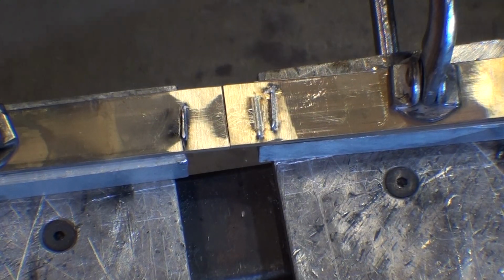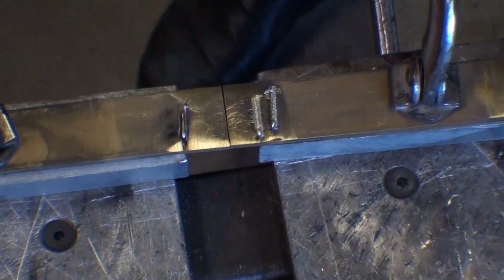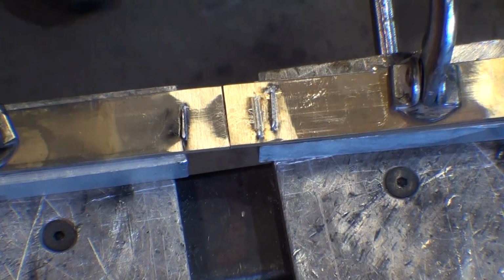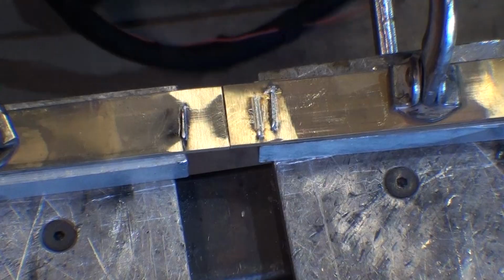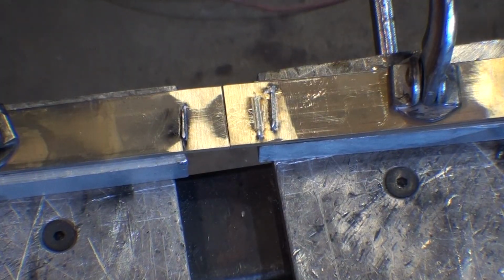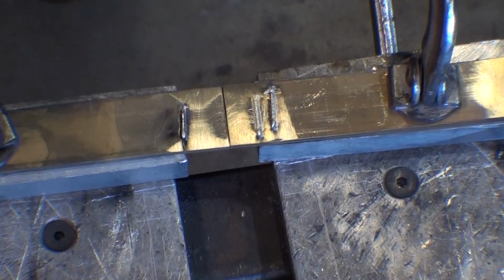Running 640 watt range modulated power settings at a 60 micron beam. The problem is the 60 micron beam in this particular challenge. If my unit were over 150 microns, it would make the task easier. The reason is that the smaller beam acts like a search and destroy pattern on the zinc elements in the metal lattice, which is why the backside shows a large number of pinholes. That's why it behaves like a band-aid cap on brass, cosmetic, not structural.